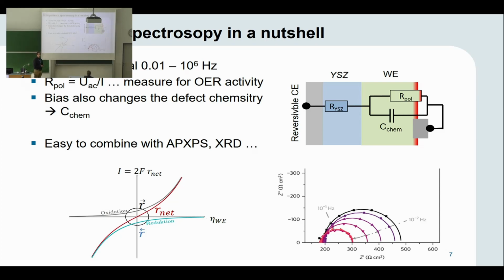I just want to give you a quick introduction into our most important characterization method, which is impedance spectroscopy. Thereby, we apply a very small AC signal to the electrochemical cell, only 10 millivolts. In this regime, current and voltage are proportional, and we can measure a polarization resistance, which is a measure for the oxygen exchange reaction activity.